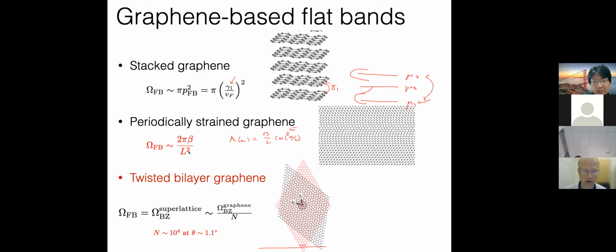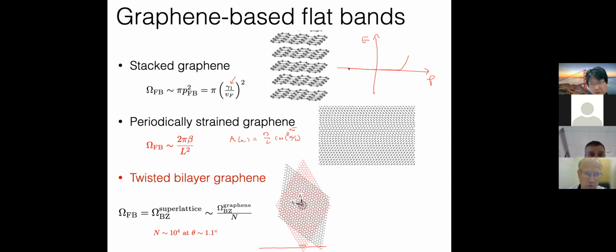Sorry. In the first case, the size of the flat band means you assume part of the band has to take the flat form. What's the meaning of this form? Okay. So compared to the previous talks in the meeting, it's indeed different. This is not an isolated flat band. What happens rather is that the energy as a function of momentum is essentially 0 up to some cutoff, and then it becomes finite. And this cutoff here is what I call the flat band radius. If you look at a 2D dependence, it's a circle, and the flat band radius is gamma 1 divided by Vf. Yeah, and that's why pi times the radius squared is the flat band size.